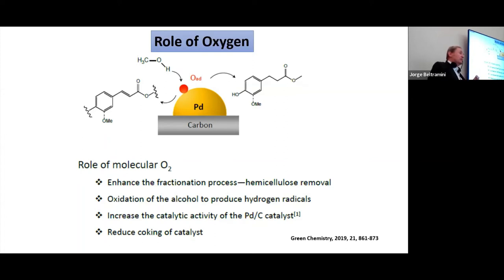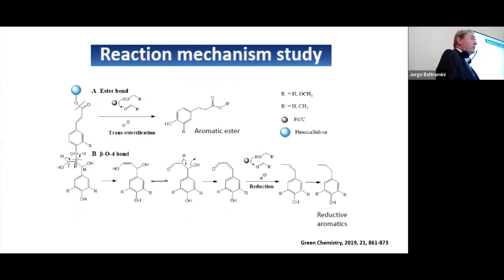It's also here that, with the oxidation of the alcohol, we produce hydrogen radicals. How do we produce hydrogen radicals? Because in close position to the palladium, we produce a spillover. The spillover of hydrogen produces hydrogen in an atomic entity that will clean the surface of the palladium and keep the catalyst working for a long time. So we reduce the coking of the catalyst. This is the mechanism, just as an illustration. We see here how we remove the hemicellulose at the beginning, and then the different steps, how the beta-O4 bond is affected in order to create these aromatic monomers and the G and the H ester.